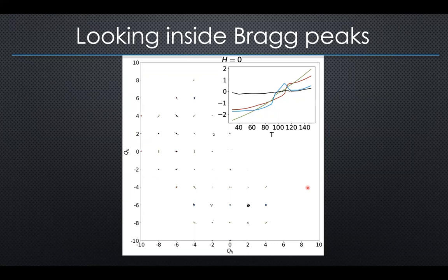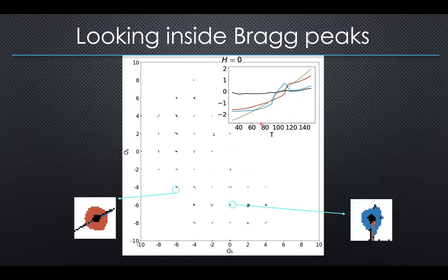For instance, if we ask for too many clusters, when naturally the data has, I don't know, three or four, let's say the data has four and we ask for eight clusters, what we will get back are different clusters that are really nearly on top of each other. So we find out, okay, that was too many. So when we opened up each vicinity of the peak, we found that there are four distinct clusters. And then you can see where those four clusters are coming from by looking at the blow up of the regions of each peak.